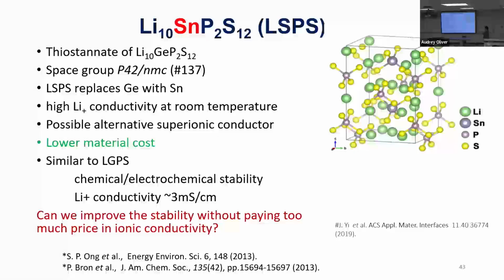I'll show some examples. With the tin, the ionic conductivity is also good, pretty similar to the original one. We call that LGPS. This is the LGPS, a high ionic conductor. We call this a superionic conductor, but it's not very stable.